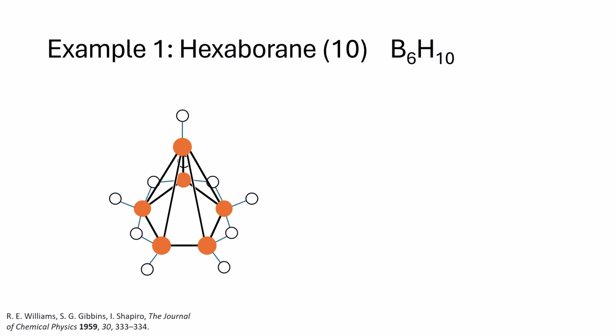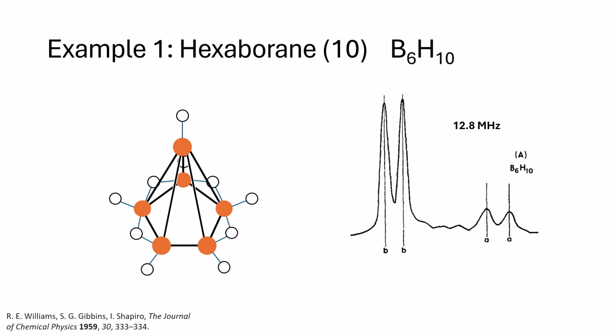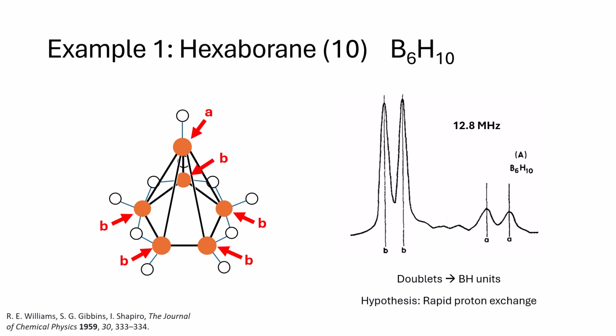So, the NMR evidence shows us that there are 2 chemical environments in this species, both of which are doublets, which easily confirms the fact that all of the boron atoms in this compound are in BH units. Furthermore, however, since this species has 4 bridging hydrogen atoms only, we would expect 4 distinct boron chemical environments, yet we only observe 2, of which all of the basal boron atoms are in the same chemical environment. Hence, this leads to a hypothesis that there was rapid proton exchange occurring within this compound.